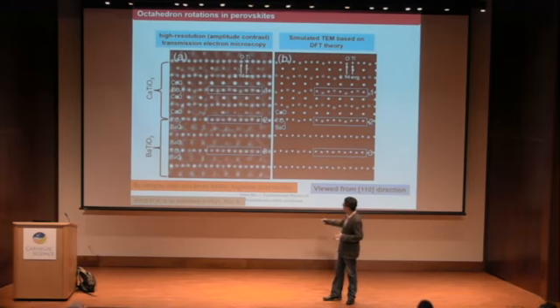For example, these dark regions - the strong dark is barium. This line is the TiO2 plane, this line is the CaO plane. So this is the Ti atom surrounded by 6 oxygens.